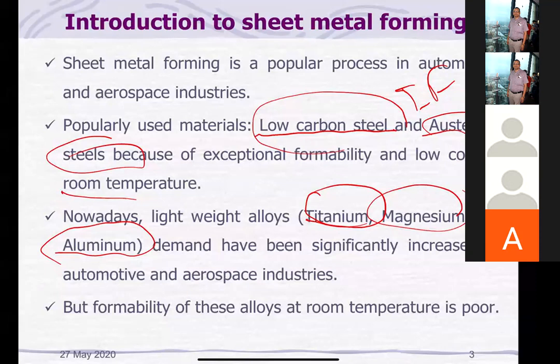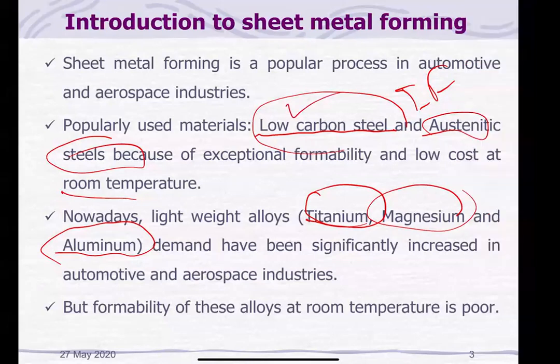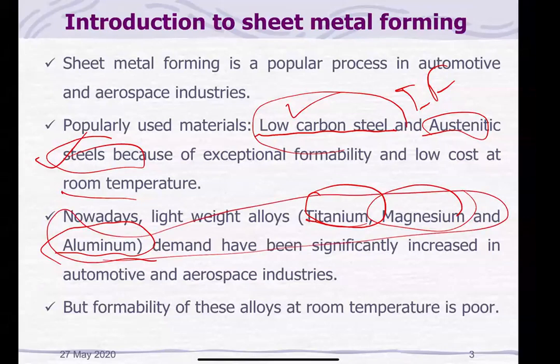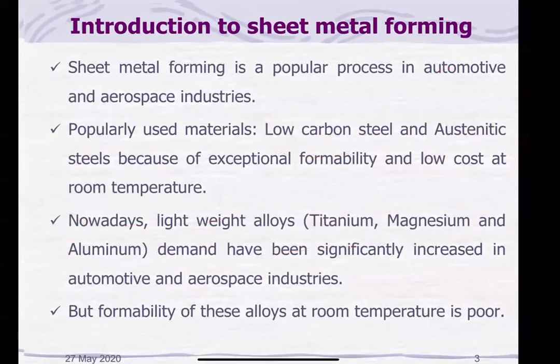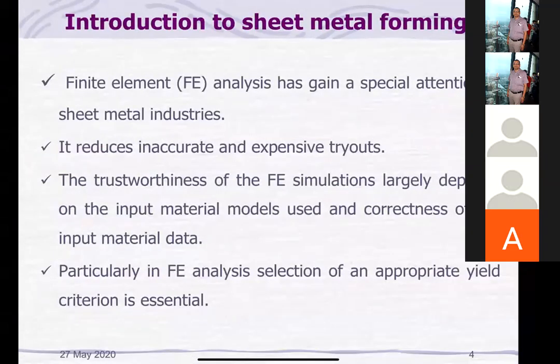Except low carbon steel and, up to some extent, austenitic stainless steel, these materials have very poor formability. All these materials like titanium, magnesium, as Professor Gupta was telling, there is a material AZ31, it has some good formability, but nothing close to low carbon steel and ASS. ASS is known to have a very good formability.